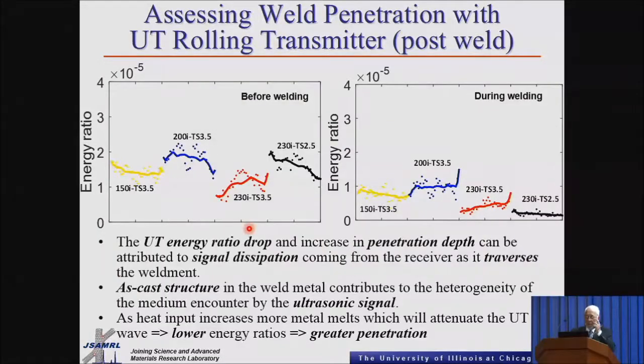So we looked at the UT, and this first one was done before welding. You can see these are the four coupons that we used. Why do you do it before welding? Because we wanted to check if there are any changes in the thickness of the plate, since even when you're getting the plates, there might be some small changes. In this case, all of them are pretty much the same. You have pretty much the same signal, which indicates probably the same thickness of plate. However, in this one there was a little drop, which might be associated with some surface roughness too.